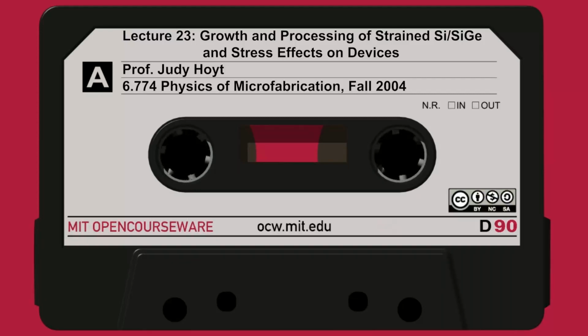So the threading dislocation density can go down from 10 to the 9th to less than 10 to the 5th if you do the grading right. So the nice thing about this is all of a sudden on silicon substrates in the early 90s, people had a way to take a silicon substrate, grow a relaxed silicon germanium layer, and have it be of reasonably high quality that you can make devices on it that work. There's still a lot of threading dislocations, but not enough to screw up the devices too badly. So that was the breakthrough that enabled people to make relaxed silicon germanium and then strained silicon MOSFETs on top of it.